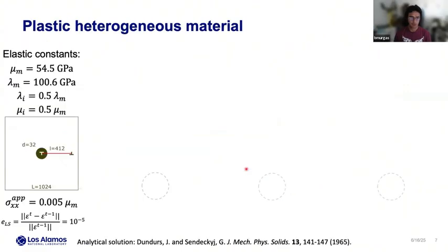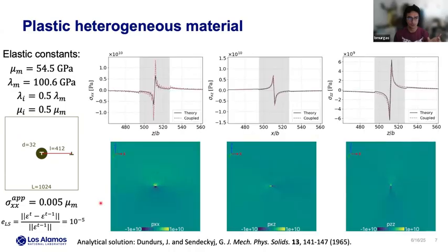After I set up the code and the solvers, we started to compare with analytical cases. There are analytical cases where you have only a matrix and a circular inclusion, but there are also really nice analytical solutions for the same case with edge dislocations inside the inclusion. You can check the analytical solutions in this reference. This is the case where I have a soft inclusion, and the solvers work pretty well for these cases.